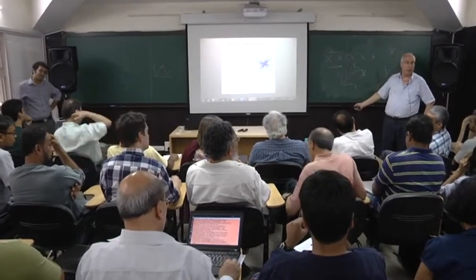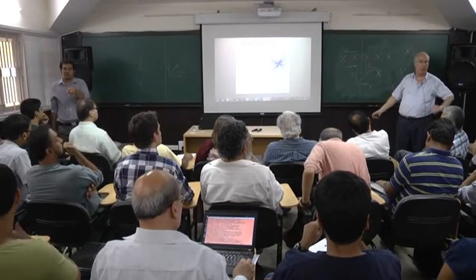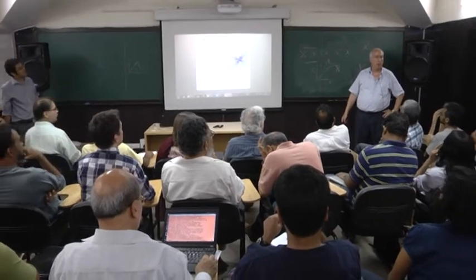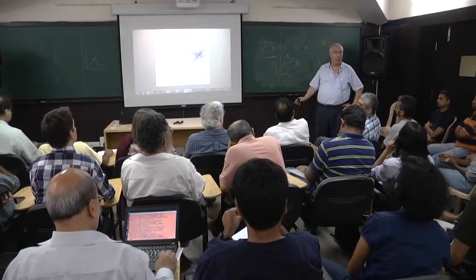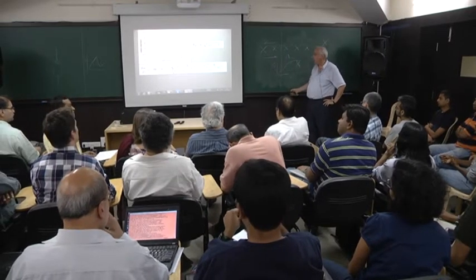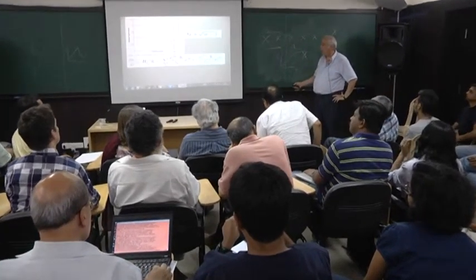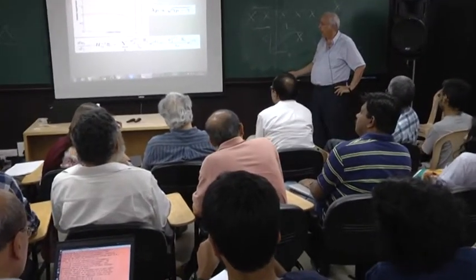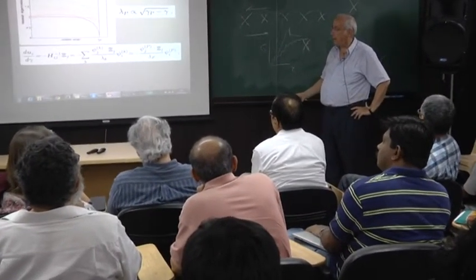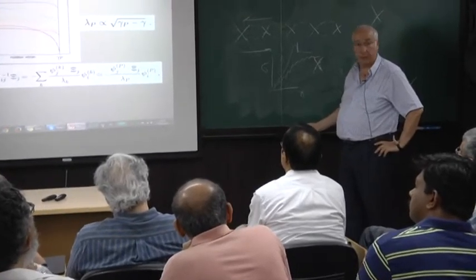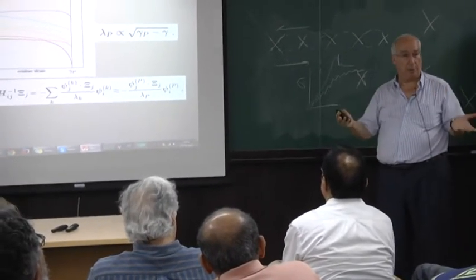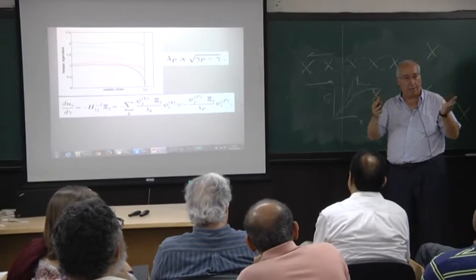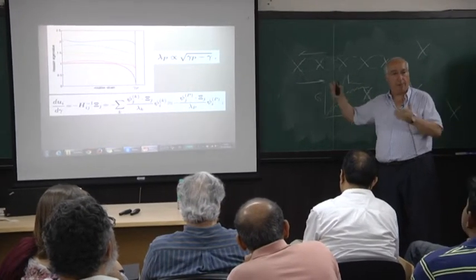This is from the displacement. This is the actual response of the system when you have a plastic instability. This is the eigenmode. It's the same. The actual response, as I showed you, when lambda is very small, when you're very close to the instability, then the non-affine displacement and the eigenfunction are actually the same object.